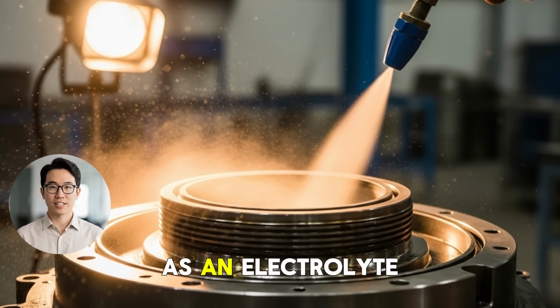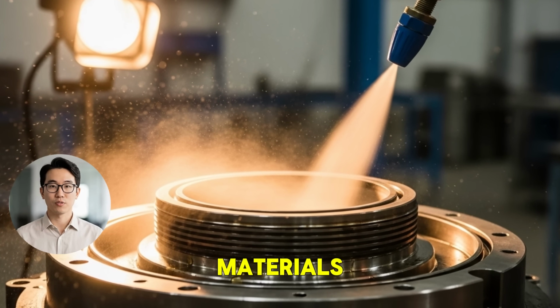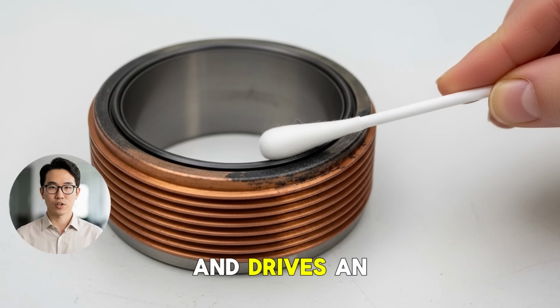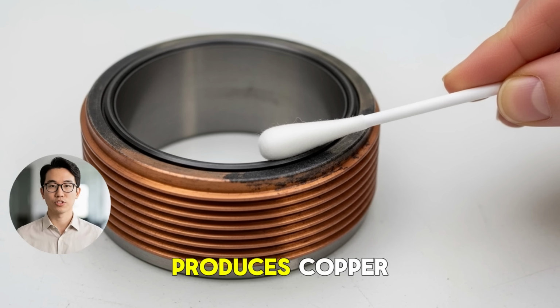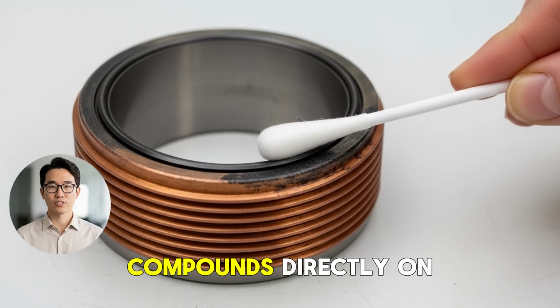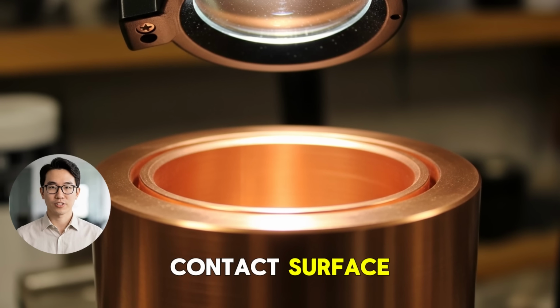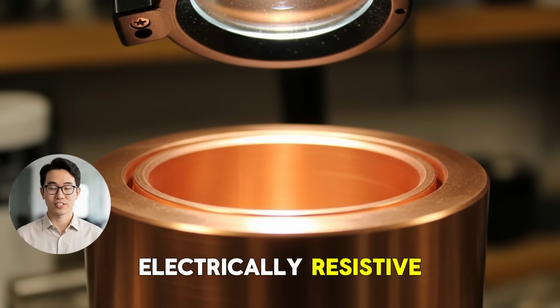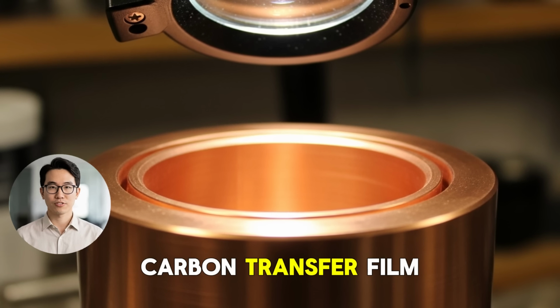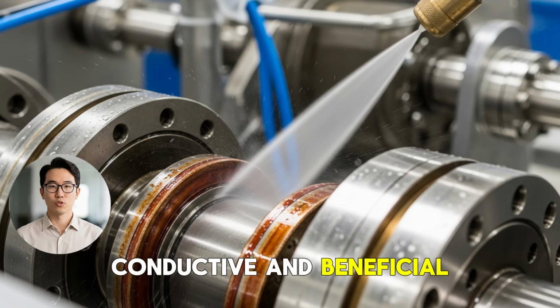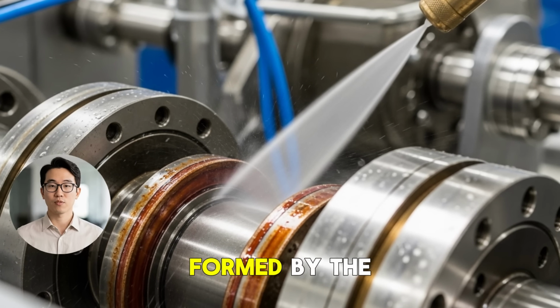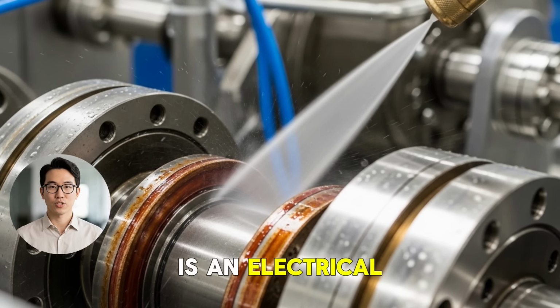The moisture acts as an electrolyte, bridging the dissimilar materials, carbon graphite and copper, and drives an electrochemical reaction that produces copper carbonate and carbon oxide compounds directly on the slip ring contact surface. These compounds are electrically resistive. Unlike the original carbon transfer film, which is slightly conductive and beneficial to brush operation, the oxide layer formed by the galvanic reaction is an electrical insulator.